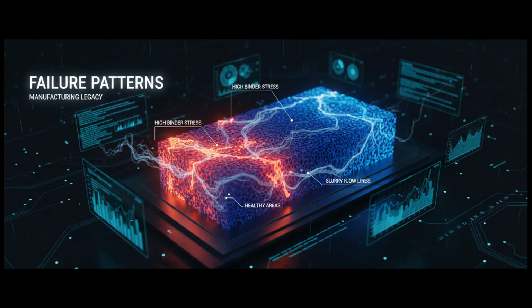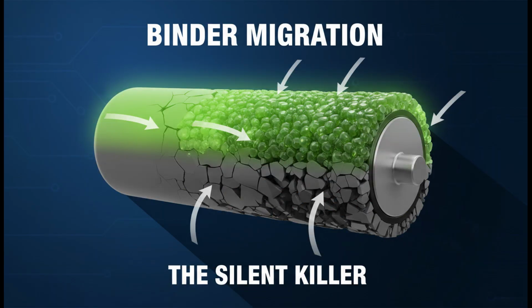But the Oxford team didn't just see the damage, they saw the cause. They discovered that the binder doesn't fail randomly. It fails in specific patterns based on how the slurry was mixed and dried months earlier. They found that in fast-charging batteries, the binder tends to migrate toward the surface, leaving the core of the electrode brittle and prone to cracking. This inhomogeneity is the silent killer of fast-charging performance.